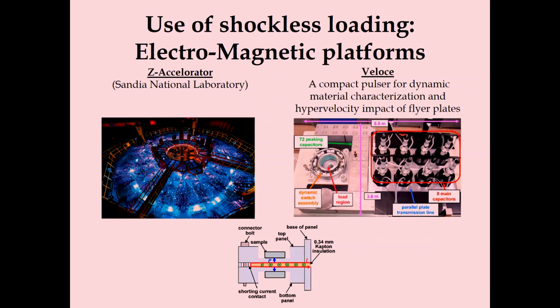And just to point out how this generally works, if we see this illustration here on the bottom, we can have a small cartoon. We're putting a lot of energy in capacitors. We're charging it up to a few tens of kilovolts, and we have a fast discharge, which is discharging a very high current of a few megaamperes. And as this current is flowing through one conductor and coming through the other, we have repulsive magnetic forces between them, and they're pushing on the material, which we could then measure.